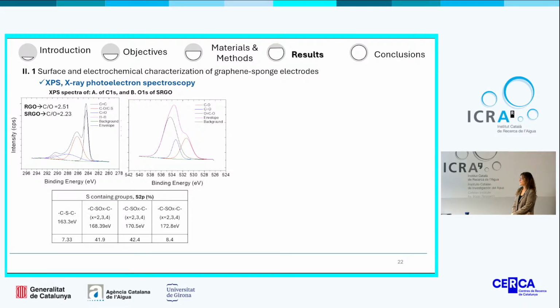Through XPS, different sulfur-containing groups were identified, as can be seen in this table. It's important to mention that the carbon-oxygen ratio comparing RGO with SRGO is a little bit lower in the case of SRGO, probably because of the different sulfur oxide containing groups in our sponge.